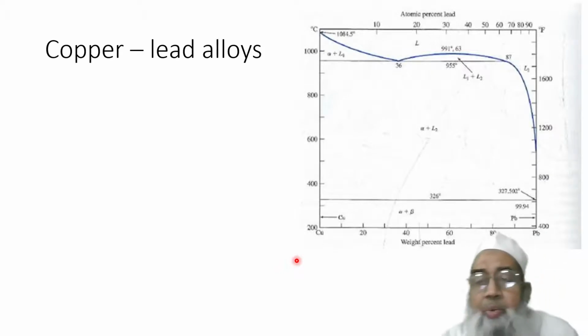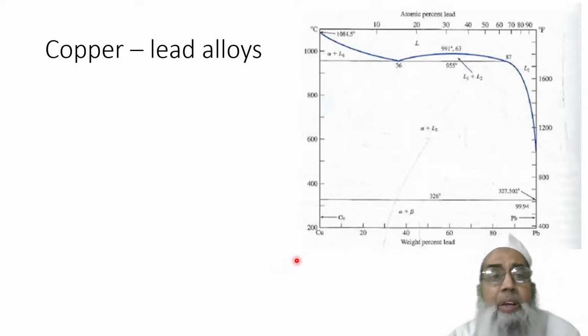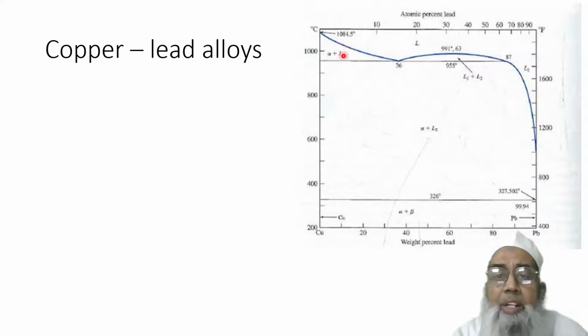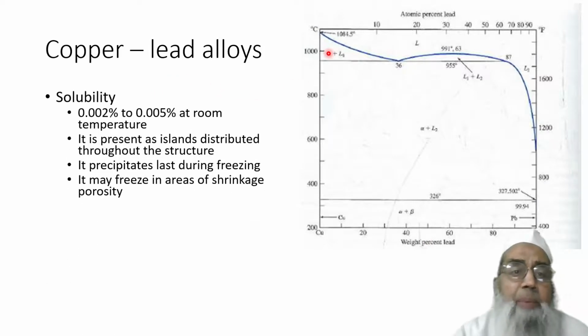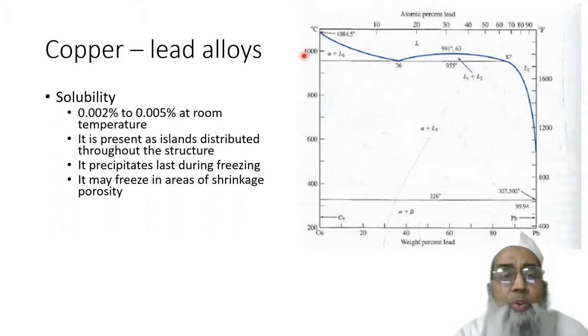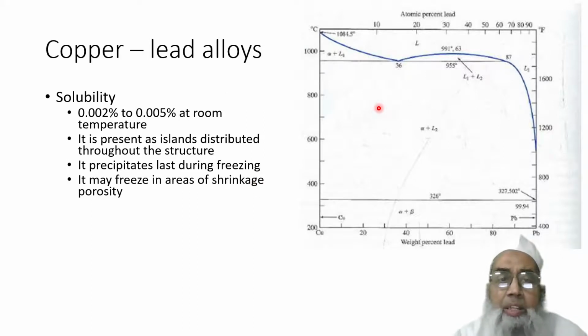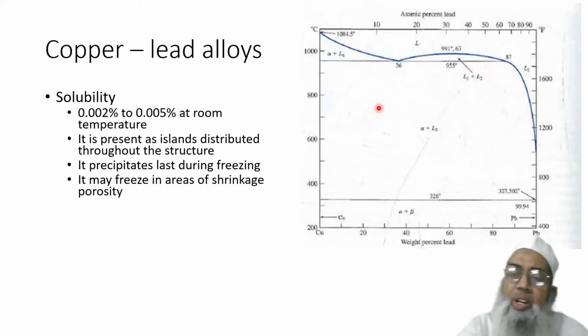Now, this gives a figure of the phase diagram of a copper and lead alloy. You see here the percentage of solubility of lead in copper is very little, about 0.002 to 0.005% at room temperature. But the very bad thing is that it is present. It is not very much miscible. Rather, it is present as islands distributed throughout the structure.